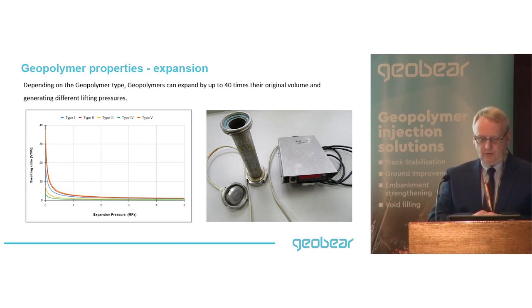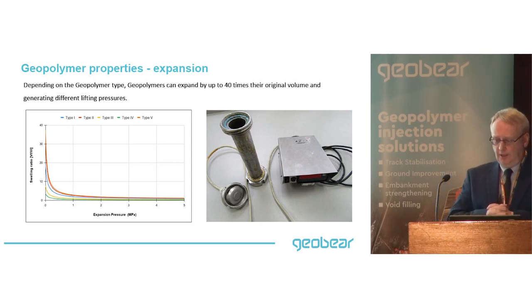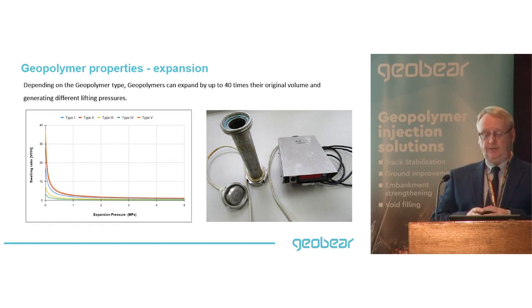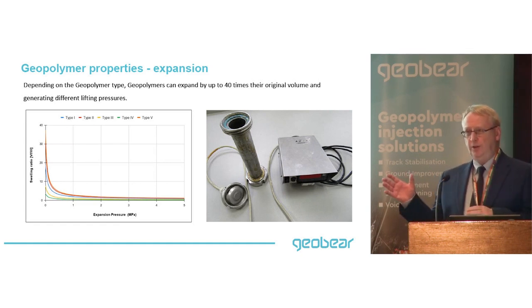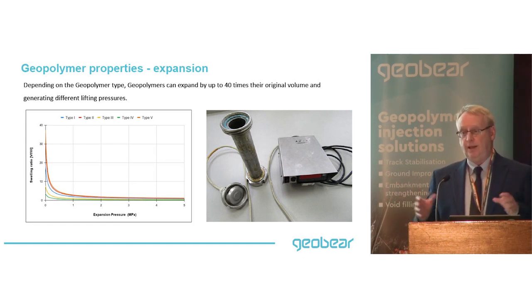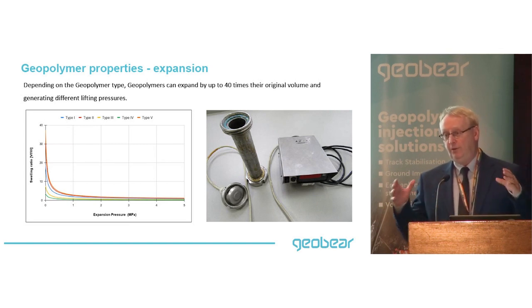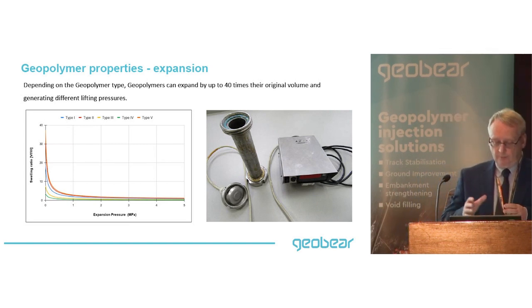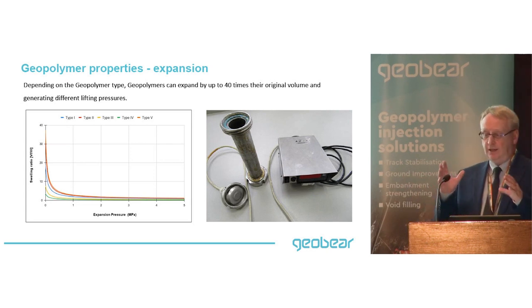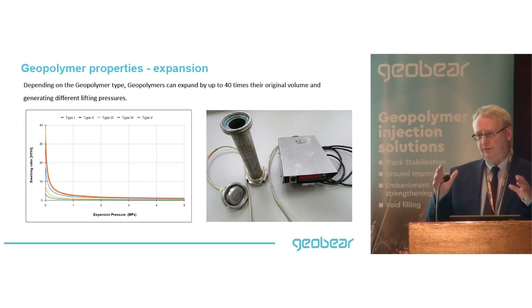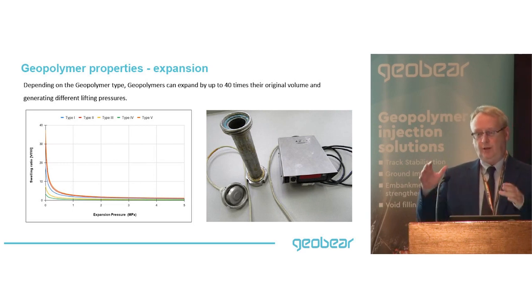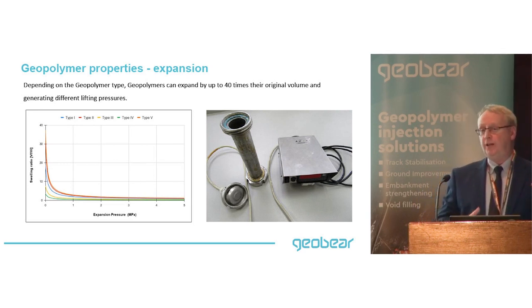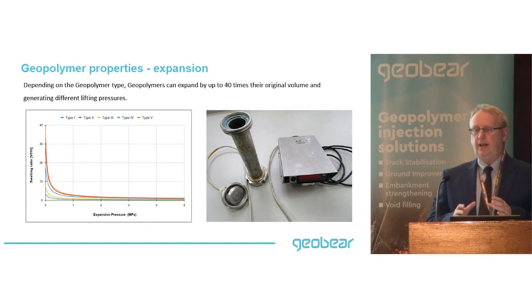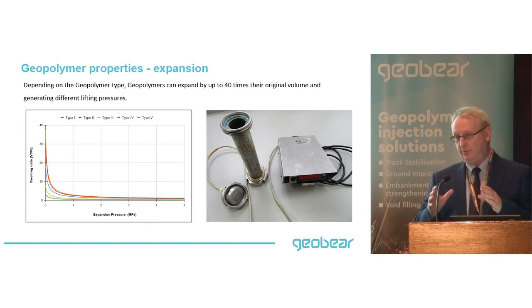Now, depending on the geopolymer type, the geopolymers can expand up to 40 times their original volume and generate different lifting pressures. And what you saw in the video clip was a high expansive volume, and that was probably up to 40-fold volume expansion. But the amount that a polymer will actually expand is controlled by the confining pressure at the point at which you inject it. And so there's a relationship between the confining pressure and the amount of expansion you get. Understanding that relationship is really important if you want to design with geopolymers.